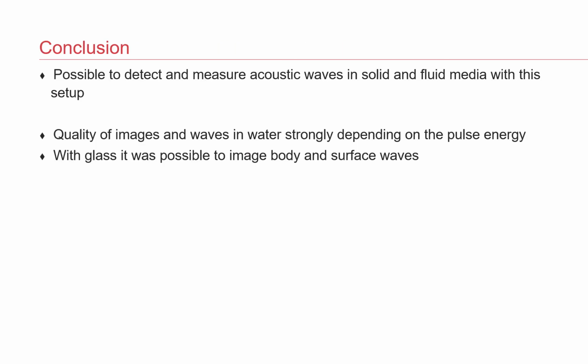To conclude, we were able to image and measure acoustic waves in solid and fluid media. The results in water show that the wavefronts are highly dependent on the pulse energy. In glass, it was possible to image the longitudinal wave by focusing inside the volume and on the surface, and also when on the surface, a possible Rayleigh wave was visible.